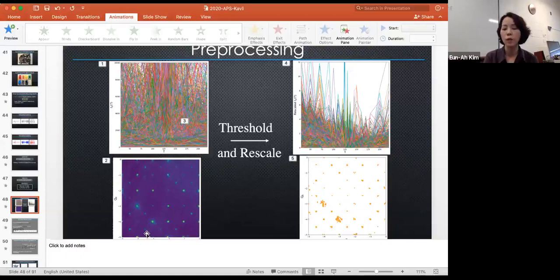And some efforts are to take the X-ray data and Fourier transform it, because the Fourier transform of reciprocal space would be something like real space, but that is also not very easy to interpret. Ultimately, there is the phase problem: when you do X-ray, you lose phase, and there's no way to remake it. There are many ways of trying to guess the phase and fit the data, and that's traditional forward modeling, and that's very expensive. So what we're trying to do here is